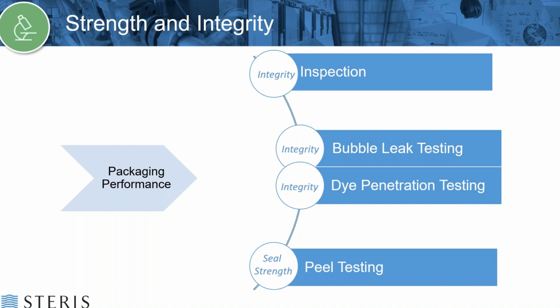Some other integrity tests include a bubble leak test, where you submerge the package underwater and inflate it with air and observe for steady streams of bubbles indicating a channel through a seal, or perhaps a pinhole, or any sort of breach in your sterile barrier. There's also dye penetration testing as an integrity test. This is where you would inject a purple dye into the pouch or the package and observe for that dye leaking through, again indicating a channel through a seal or some sort of breach in that sterile barrier integrity.